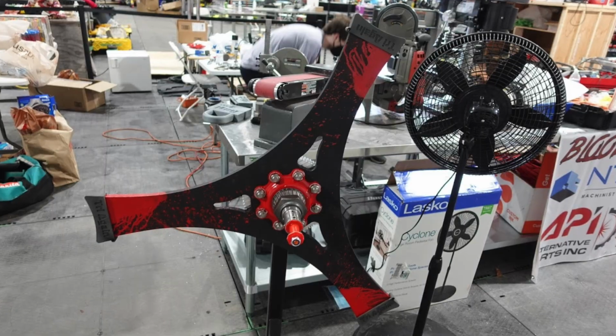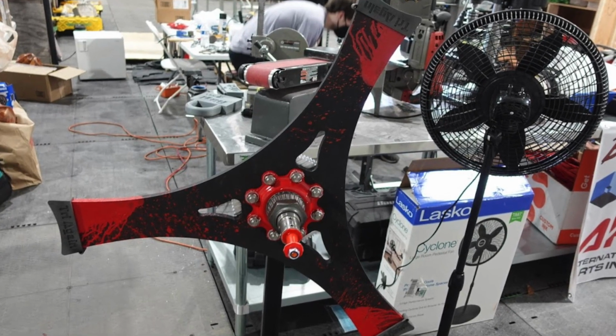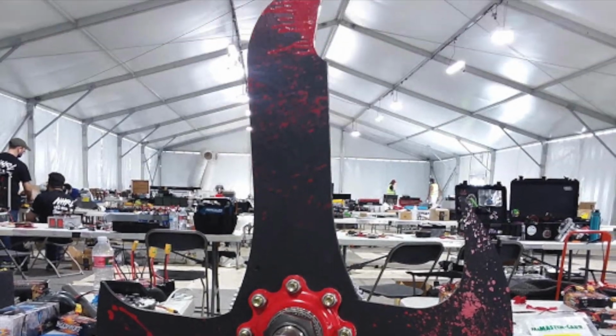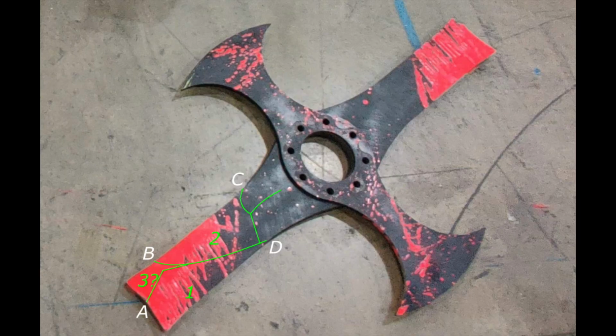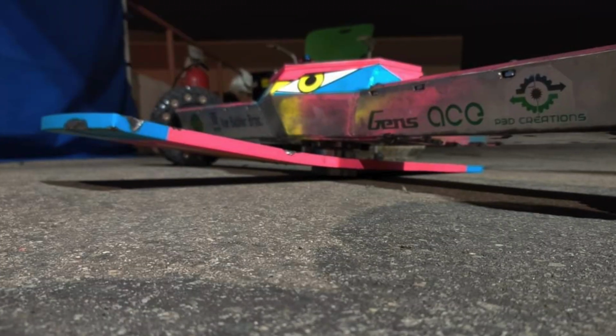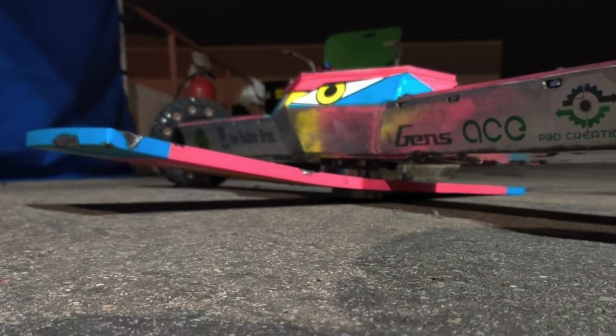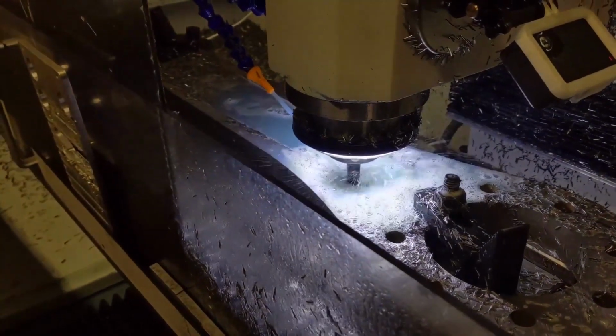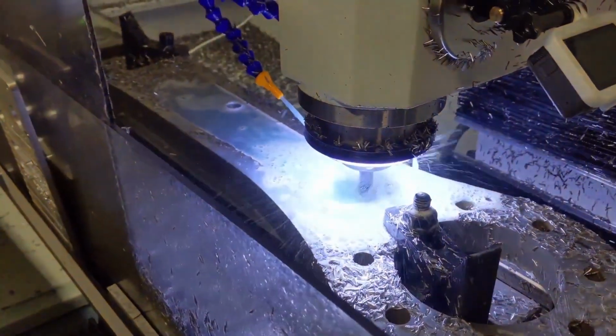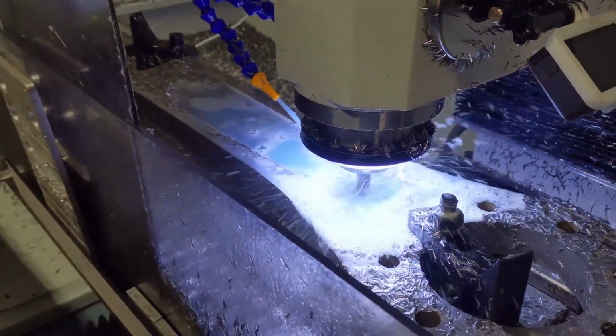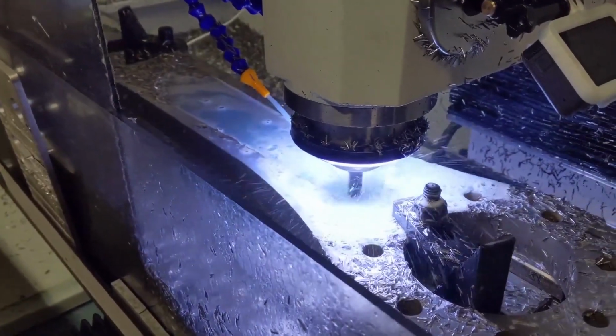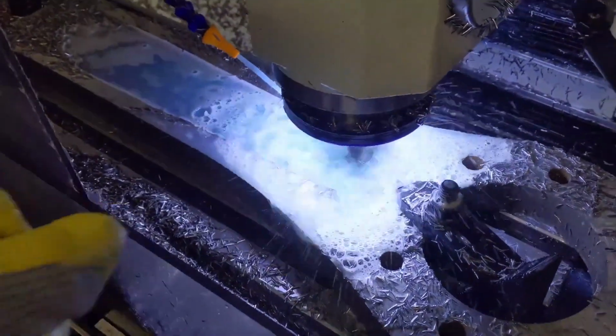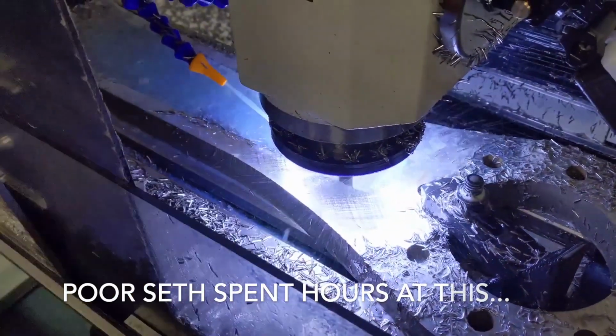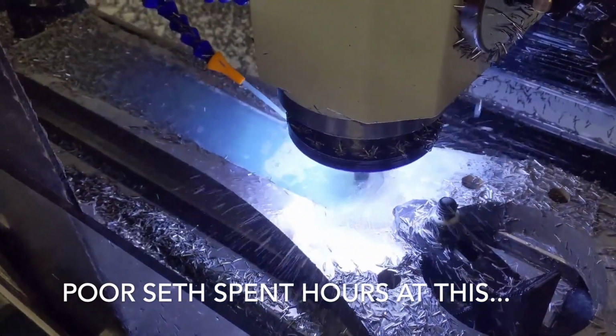Add in the reach issues that old blade has, and it's clear we need to try something else. So why not just remake the THICC Bar in AR-500 like we did with Try Again and the Classic Bar? That's where our minds went first, but there are a few problems. In this case, where S7 breaks, AR-500 will likely bend. A bent weapon is better than a broken one, but then there's also another problem. The THICC Bar was pocketed. You'd have to be completely insane to try to machine pockets like this into an AR-500 bar. It only worked for us because S7 can be machined and then heat treated.